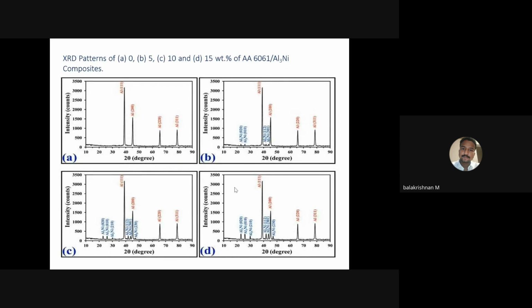Then Al3Ni at 5, 10 and 15 weight percentage. Till 5% there is no formation of Al3Ni intermetallic. After 5 we will observe some peaks in this one. After 10 we can observe more. After 15 weight percentage we can observe more number of Al3Ni intermetallic composite peaks.